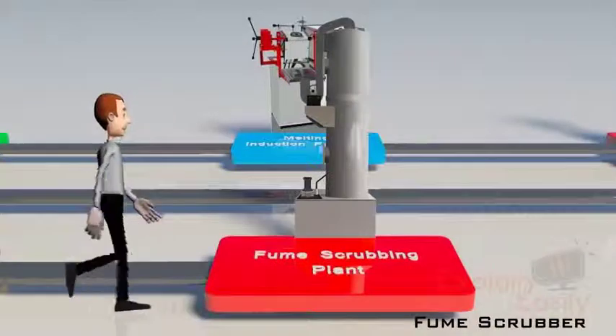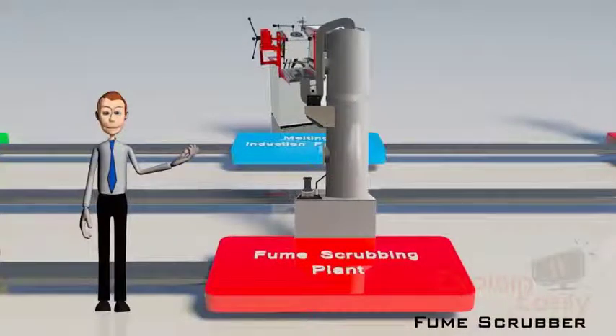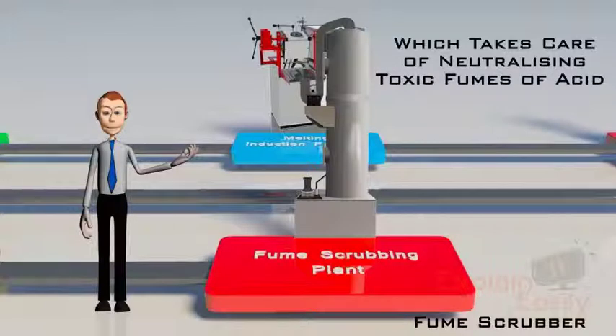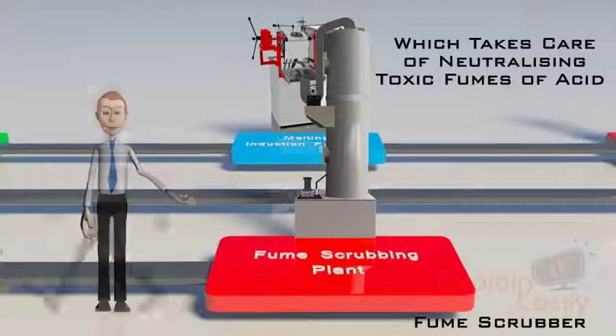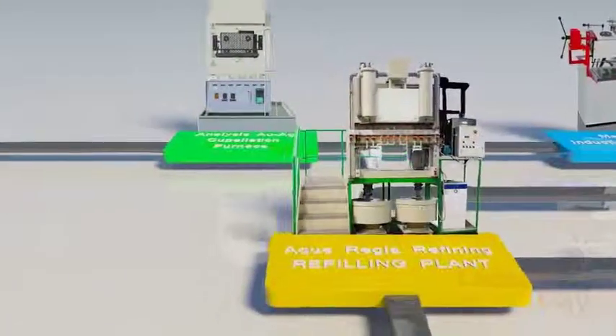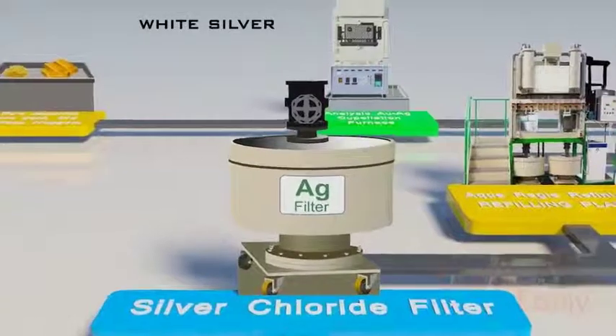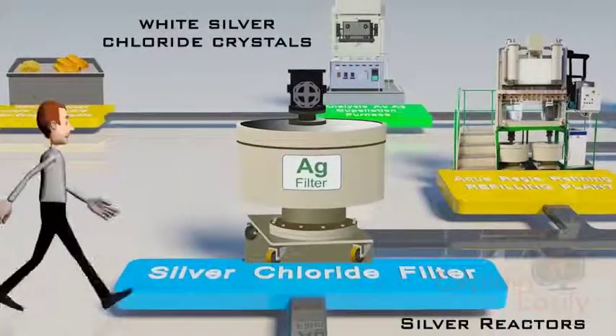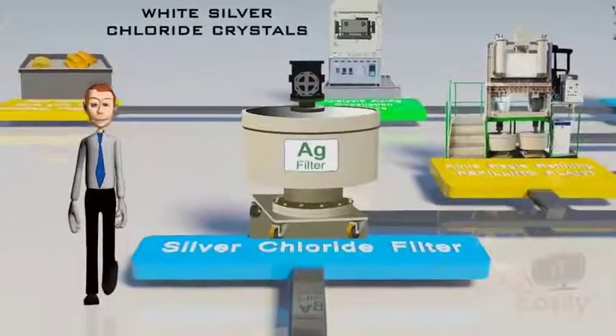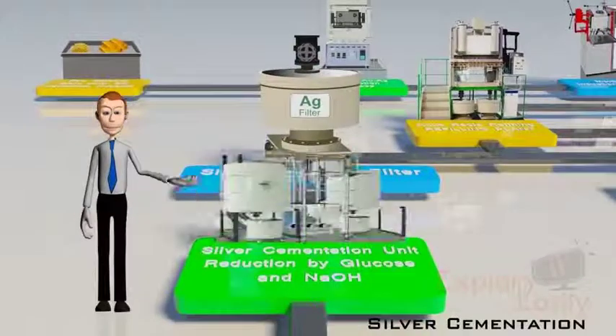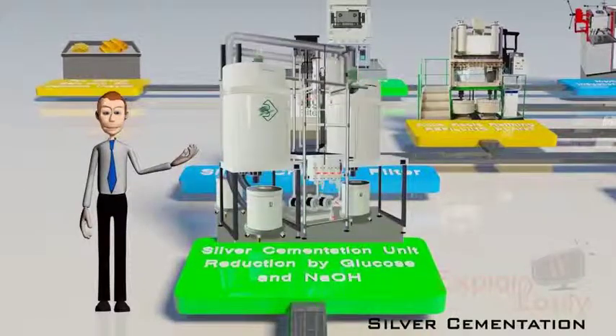This aqua regia reactor is connected to a fume scrubber, which takes care of neutralizing toxic fumes of acid, mainly NOx generated due to nitric acid and also hydrochloric acid vapors. Silver gets converted to white silver chloride crystals, which are filtered in the silver chloride filter, and once it is ensured that entire silver chloride is filtered, then these silver chloride crystals from the filter are collected and accumulated.